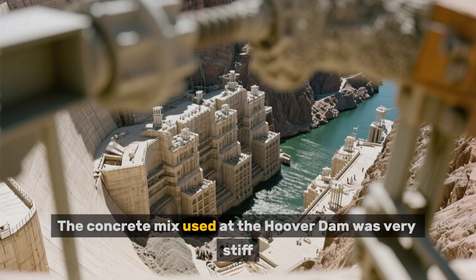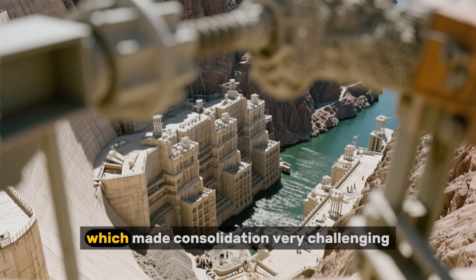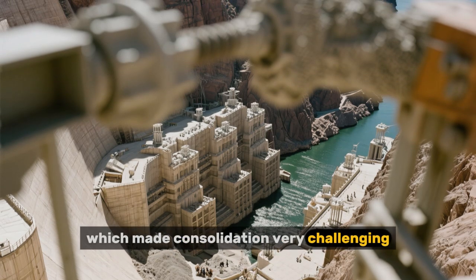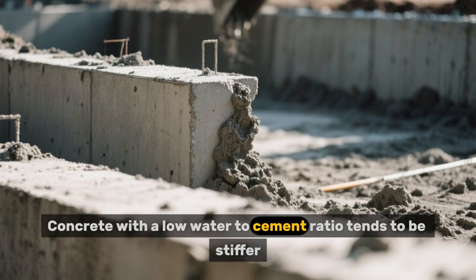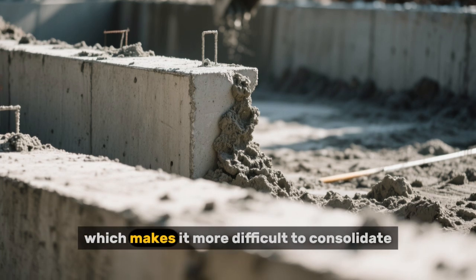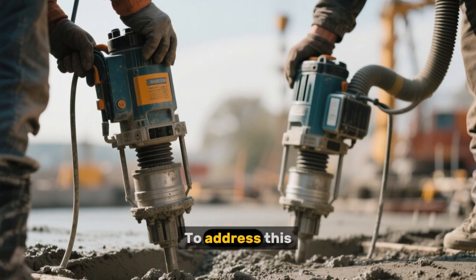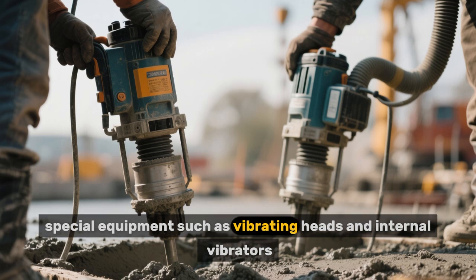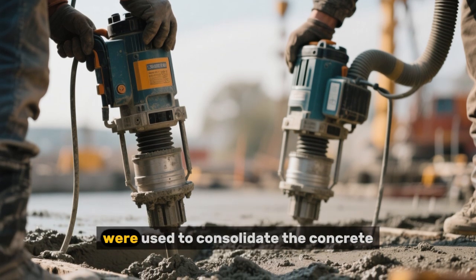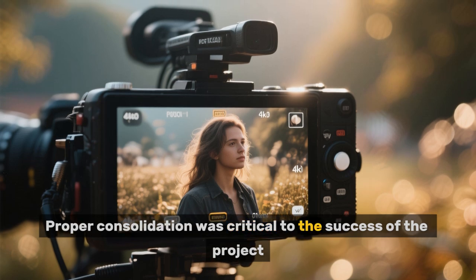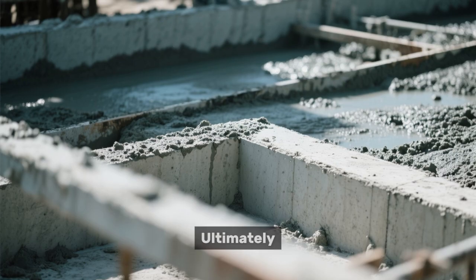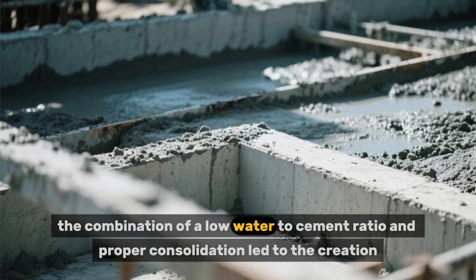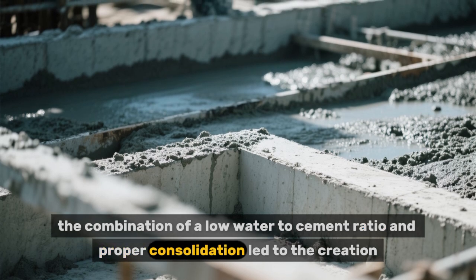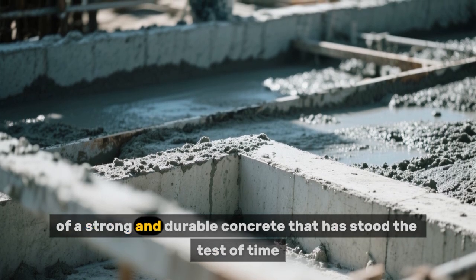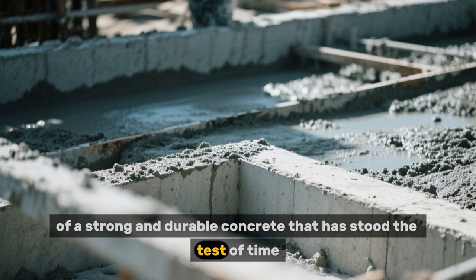The concrete mix used at the Hoover Dam was very stiff, which made consolidation very challenging. Concrete with a low water-to-cement ratio tends to be stiffer, which makes it more difficult to consolidate. To address this, special equipment such as vibrating heads and internal vibrators were used to consolidate the concrete. Proper consolidation was critical to the success of the project. Ultimately, the combination of a low water-to-cement ratio and proper consolidation led to the creation of a strong and durable concrete that has stood the test of time.